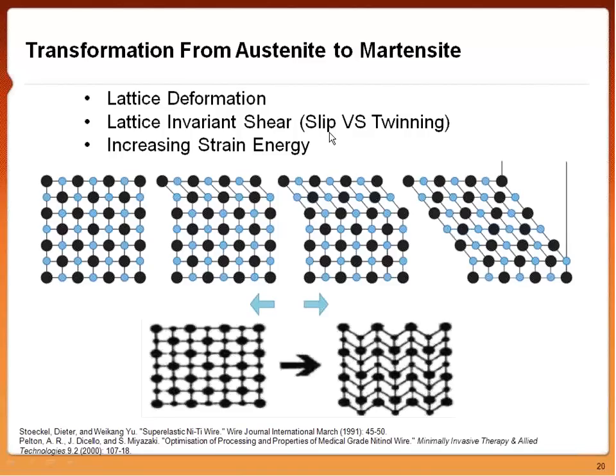The two mechanisms that typically happen within structures are slip and twinning. So the lattice invariant shear allows these new pockets of material to populate within the austenite matrix. It allows the material to fit into shape. With slip, you have basically the new structure being crammed into the other one, and you have dislocations forming, and in a sense, you're deforming the material, or possibly deforming the material. With the increasing martensite within nitinol, you have increasing strain energy as you're moving from one crystal structure to the next, which plays an important role in nitinol's thermodynamics.